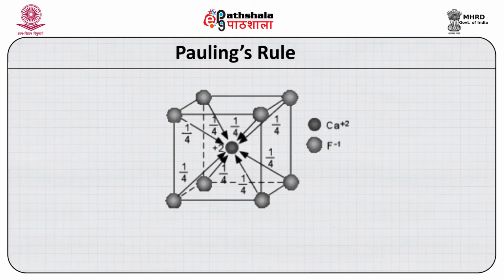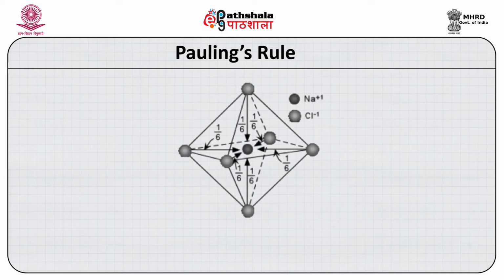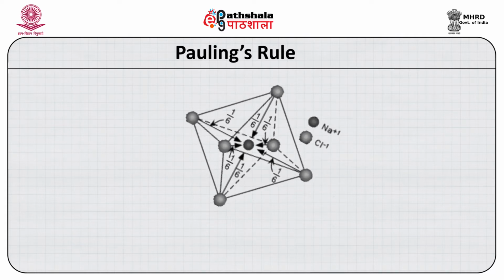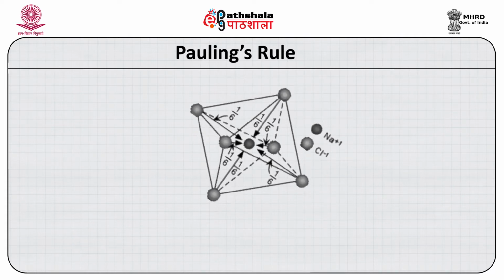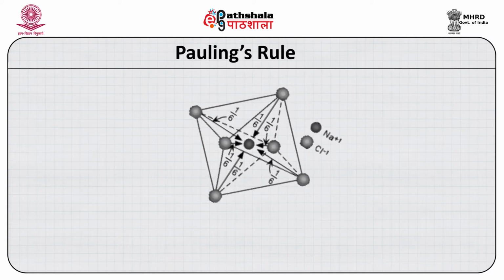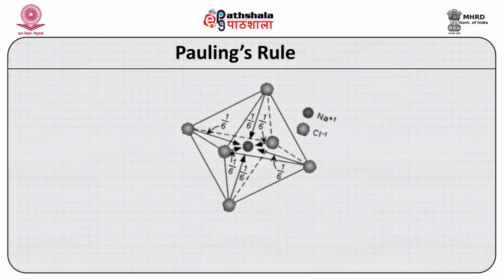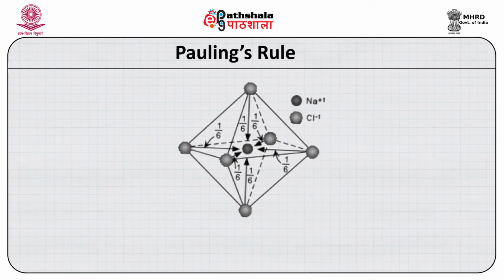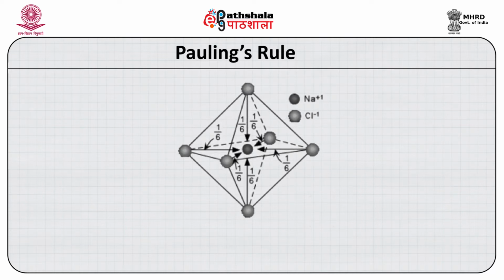In case of NaCl, each positively charged sodium ion is surrounded by 6 chlorine ions with a single negative charge. In the octahedral coordination, the coordination number is 6, the charge is 1. So, it works out to be 1 by 6. The strength of the negative charge which actually affects the Na ion is 1 by 6. Hence, one positive charge is balanced by the 1/6 negative charge of 6 Cl ions. If we multiply 6 by 1 by 6, it works out to 1.